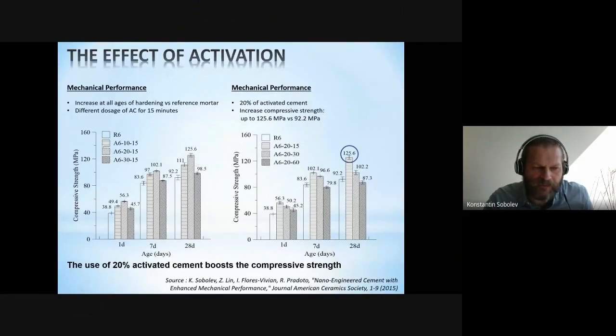And if you look at mechanical performance, we had different quantities of activated product and different activation times. We realized that even a small activation time and a relatively small quantity of cement substitution with activated cement really results in considerable improvement of compressive strength. You can see a reference material of the same composition, and I'm just referring to 28 days, but the same considerable improvement can be reached in 1 day as well.